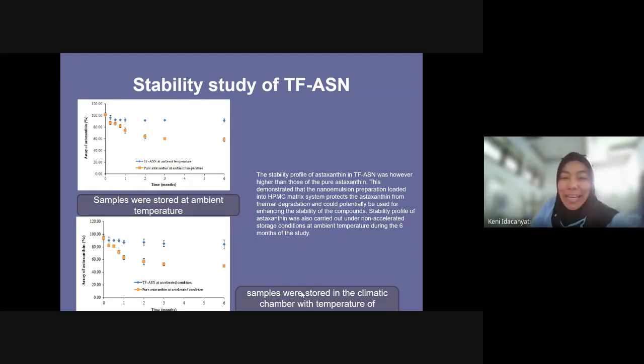RH. And the results, the stability profile of astaxanthin in thin film astaxanthin was higher than that of the pure astaxanthin. This demonstrated that the nanoemulsion loaded into the HPMC matrix system protects the astaxanthin from thermal degradation and could potentially be used for enhancing the stability of the compound. Stability profile of astaxanthin was also carried out under storage condition at ambient temperature during the 6 months of